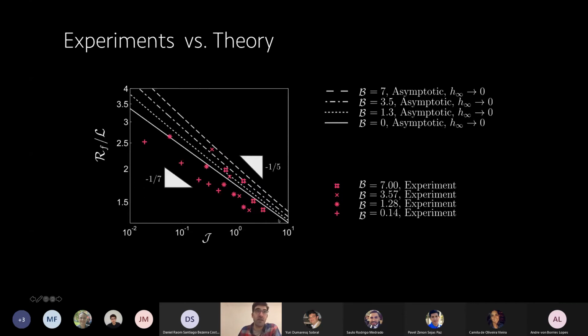So there are some good things. First of all, the experiments at low Bond number seem to be following our scaling law, which is -1/7. And as I increase the Bond number, they look like they're getting to -1/5. So that's nice. But when I compare the asymptotics with the experiment, yeah, there are discrepancies, and that bothered us. And we tried to solve it, and we tried to think what can go wrong.